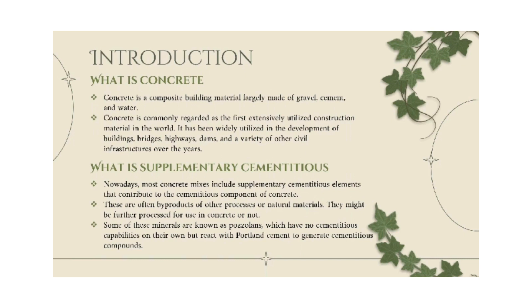Moving on to supplementary cementitious materials. Nowadays, most concrete mixes include supplementary cementitious elements that contribute to the cementitious component of concrete. These are often by-products of other processes or natural materials. Some of these minerals are known as pozzolans, which have no cementitious capabilities on their own but react with Portland cement to generate cementitious compounds. Supplementary cementitious ingredients have shown to be effective in meeting the majority of the requirements for long-lasting concrete, and blended cement are now widely utilized across the world.